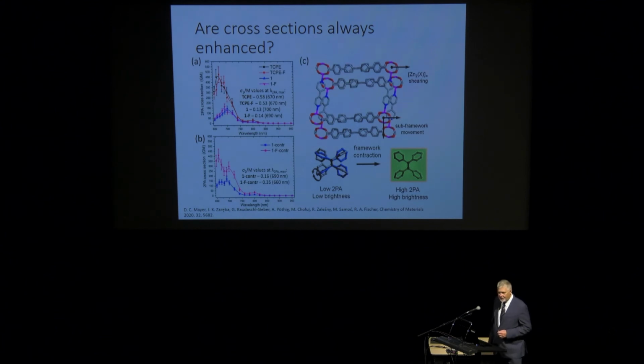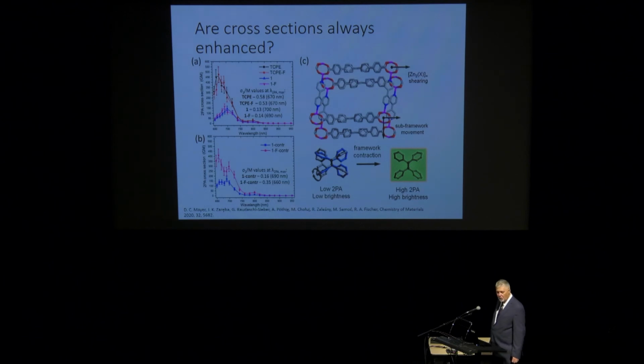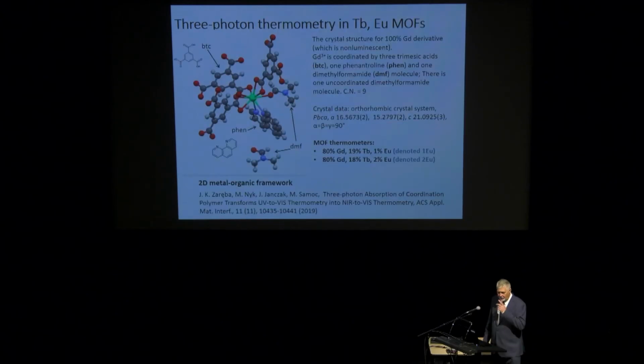Even worse, there is an example where we made a very nice MOF containing interesting ligands, which should be AIE ligands, and unfortunately, the MOF has a lower value of the cross-section than the ligand itself. But if you contract the MOF, and it contracts by itself when heating, actually the cross-section increases again. So no, that wasn't a good attempt, but it just shows that things are complicated. We do not really understand all the mechanisms that lead to this aggregation-induced enhancement. Okay, the end. Not yet.